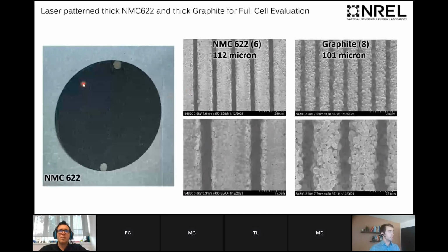So we can see, this is a photograph. You can see the channels going from top to bottom here. These two areas of circular removed material are for welding onto the coin cell current collector. With 6C, we need very good electrical contact to the current collectors, so we weld. And these are the channels on the NMC and the graphite.